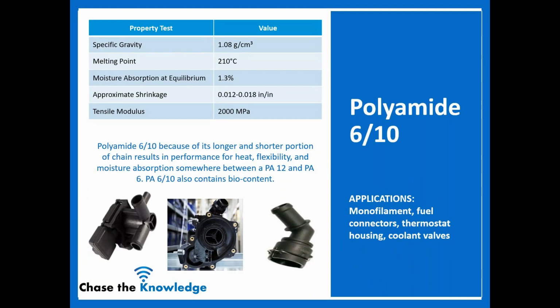Okay. Polyamide 610, similar to the 612, you're going to end up with heat, flexibility, and moisture somewhere between the two again. So pretty close actually to the performance of the 612. Your 610 is about 2000 MPa. So we started at 1400 for the 12. We went to 2200. We're at about 2000 for this one. So kind of in the middle, which you'll see as we get to the 6 and the 6.6.